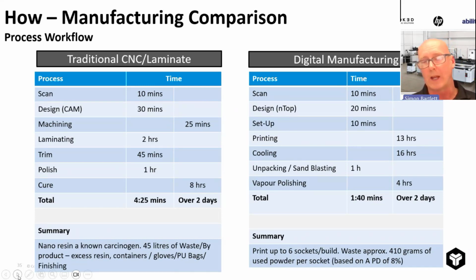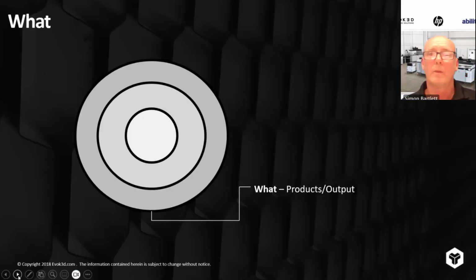Now, on the flip side, if we look at the printing process, printing 6 sockets at a time equates to a packing density of about 8%. When I say packing density, that's the number of parts that we can physically fit into a build chamber. Working on that packing density, we see a waste of around 410 grams per part, which is used powder consumed in the process. If you compare those 2 items, we've not only got a time compression, but also really big improvements in terms of our green footprint.